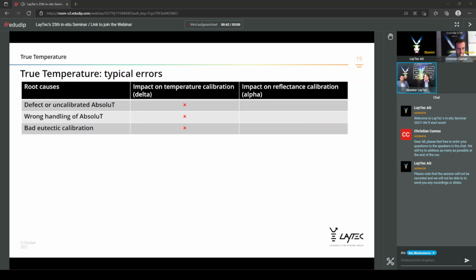Some users still like to use eutectic wafers for calibration, and they definitely have established and qualified a reliable and repeatable procedure to do that. Although we sometimes see and get reports that apparently the evaluation of the state-changing spot of the eutectic wafer has either not been met correctly or maybe the thermal process to reach that specific temperature hasn't been maintained well enough or has been too quick, so that the users missed the spot and then calculated or derived a wrong temperature spot to calibrate for the delta calibration.